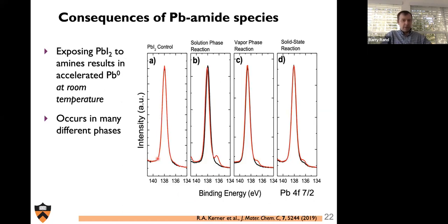What we noticed as a consequence of lead iodide interacting with amines was the formation of lead zero. So where the lead iodide control remains quite stable at room temperature and under the X-ray conditions given by XPS, if we expose lead iodide to solution amines, in this case butylamine, or vapor phase, in this case methylamine, or even solid state, in this case a very thin film of polyethylenimine, a polymerized primary amine on top of lead iodide, we could see that rather rapid exposure to X-rays formed lead zero, metallic lead, in these systems.